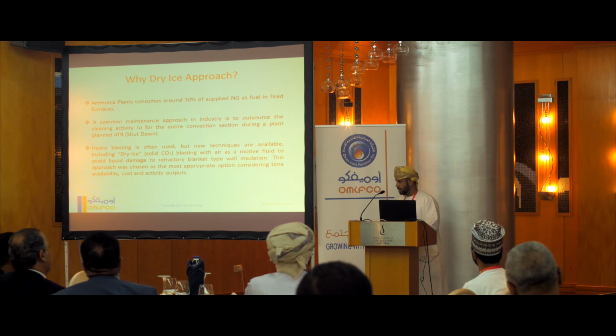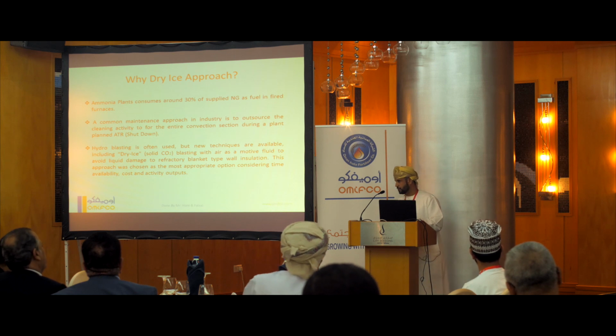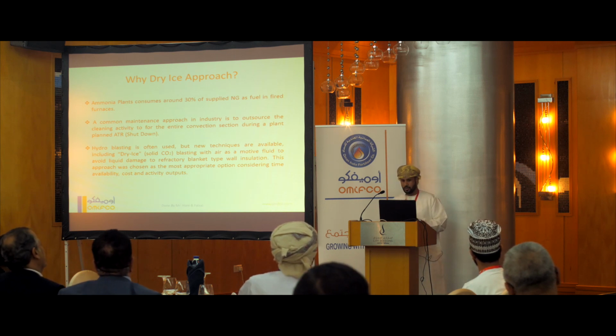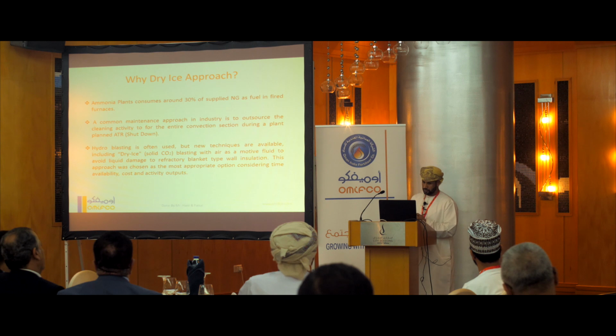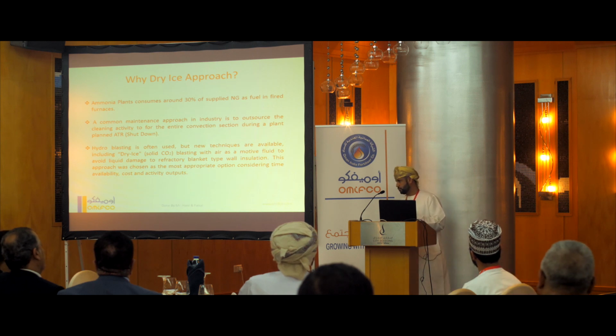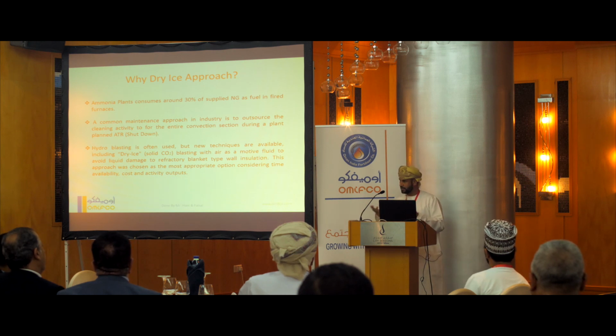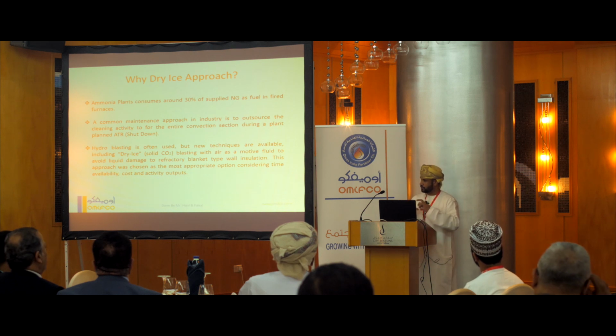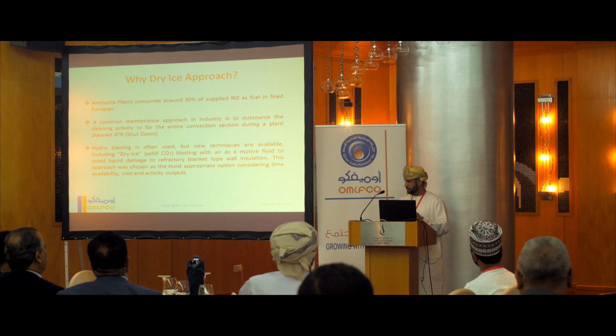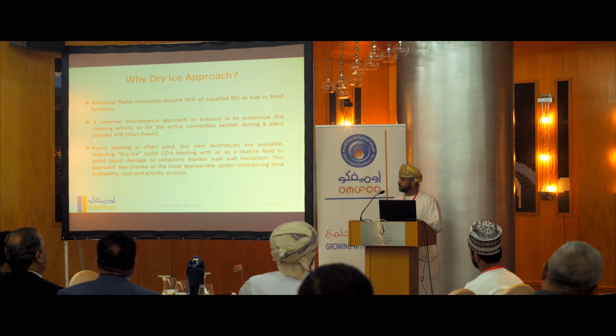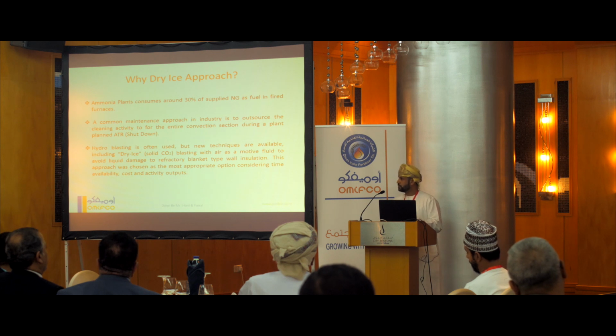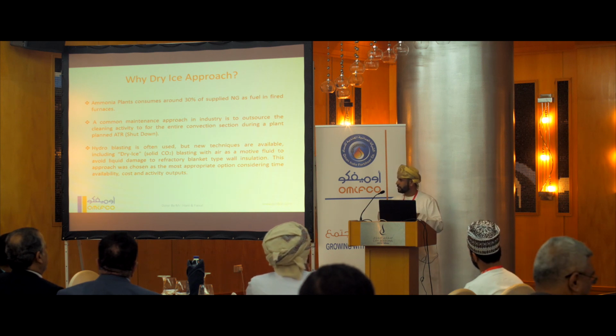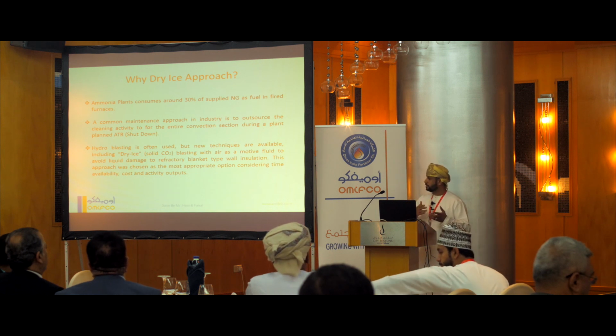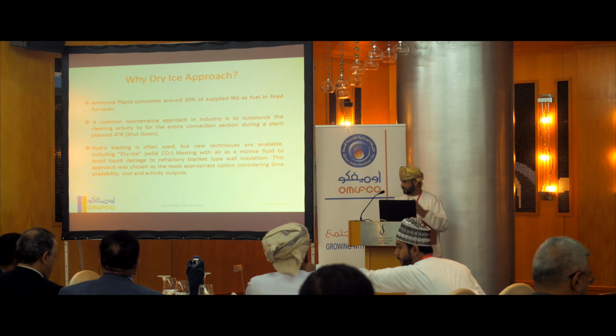Hydroblasting was often used before, we have used it, but the performance was not as good as dry ice. Techniques are available, including dry ice blasting. It avoids liquid damage to the refractory, because normally we are using water, and there is refractory on the sides and the bottom of the waste heat section, so it can be damaged. Sometimes it is damaged by the water when we use the water jet to remove the dirt. Even when there is not much dirt, it can be removed by vacuum. It is very easy to remove and does not affect the waste heat section much.